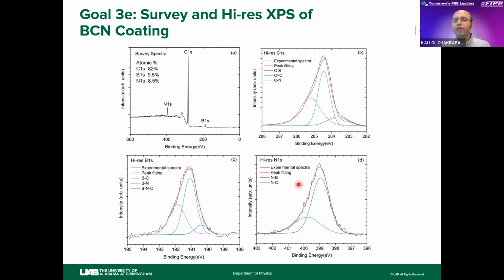After depositing the BCN material, we performed X-ray photoelectron spectroscopy to get the atomic percentages of boron, carbon, and nitrogen. According to the survey spectra, the atomic percentage of carbon is 82%, and boron and nitrogen are 9.5% and 8.5% respectively.